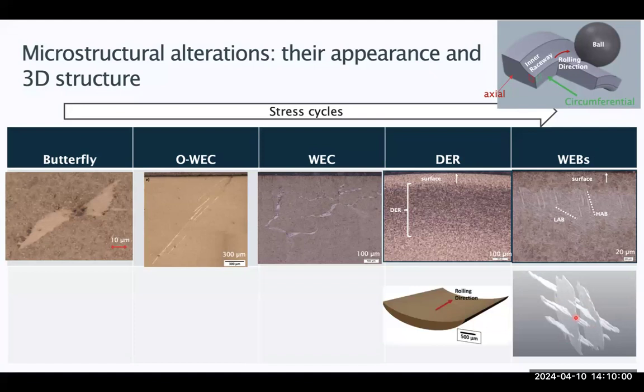Dark etching regions, people probably understand more, that they have a sickle shape in the axial direction. They look like a sickle, thicker in the middle of the contact region, but thinner towards the edge of the surface. But if you look in the circumferential direction, they just look like a band. It depends on where on the thickness of the ring you're looking. The apparent thickness of the band is different. For example, at the contact center it's thicker, but at the edge, the thickness of the band becomes thinner.